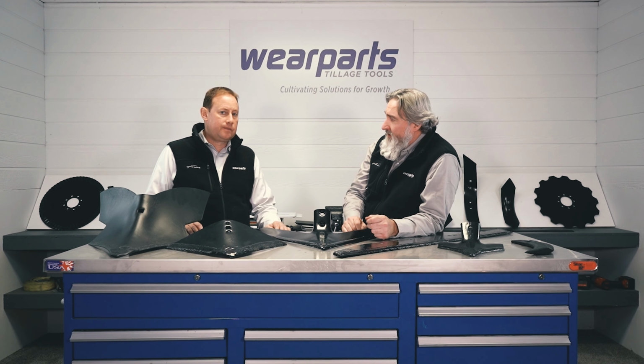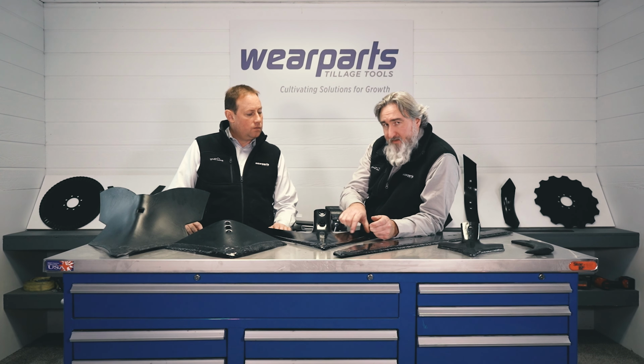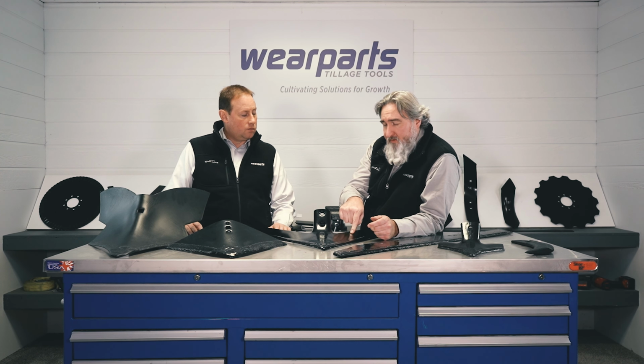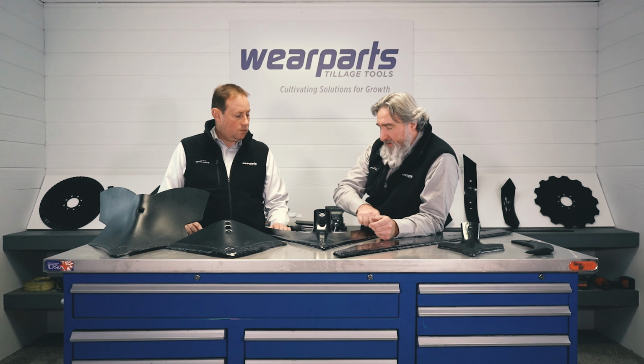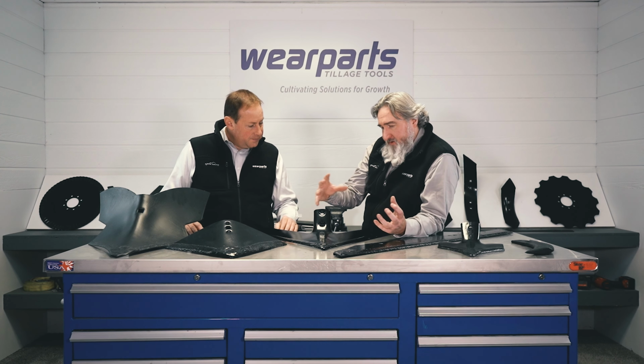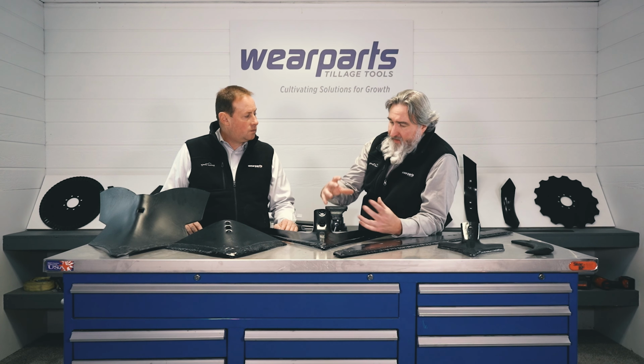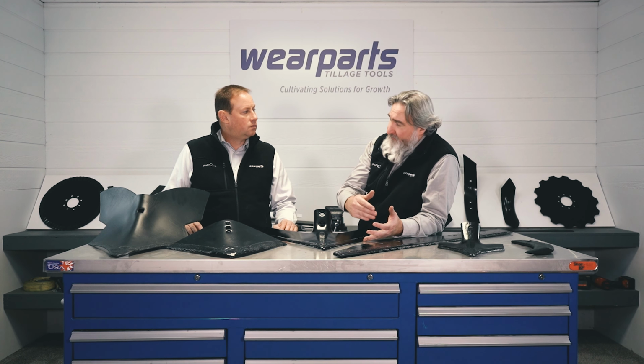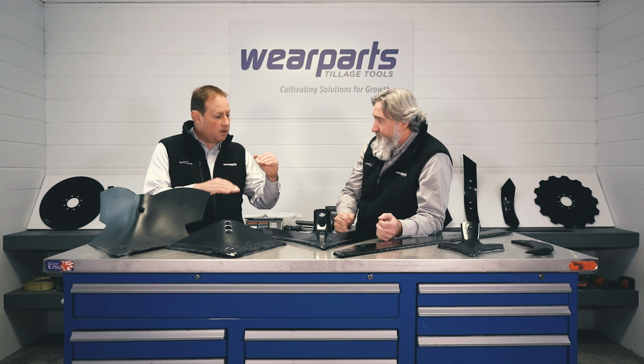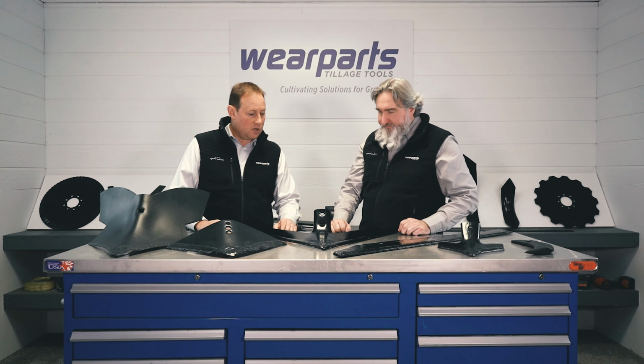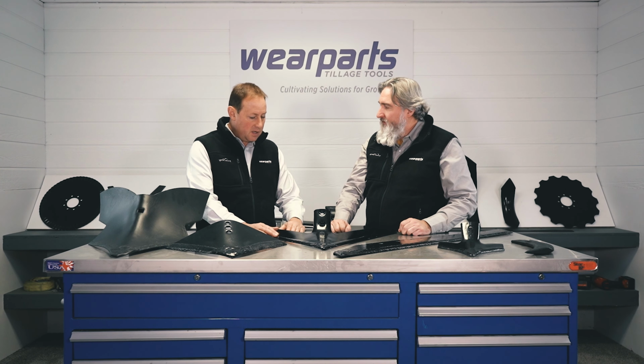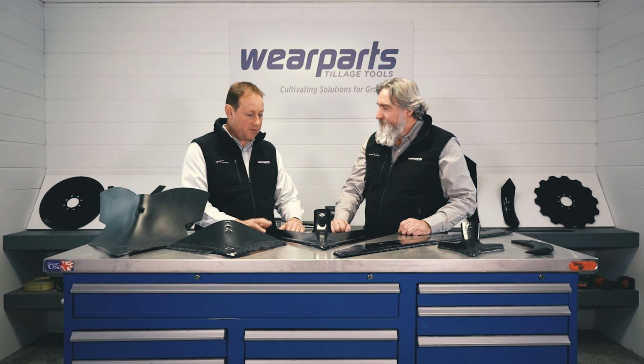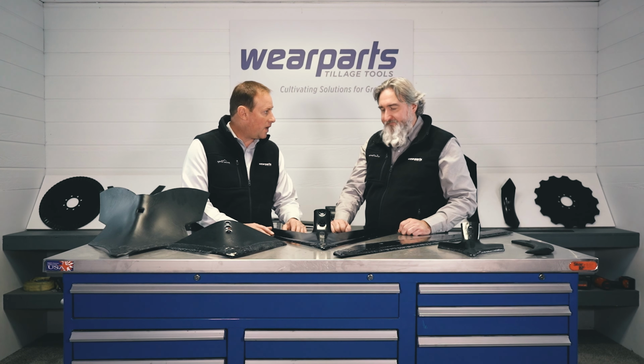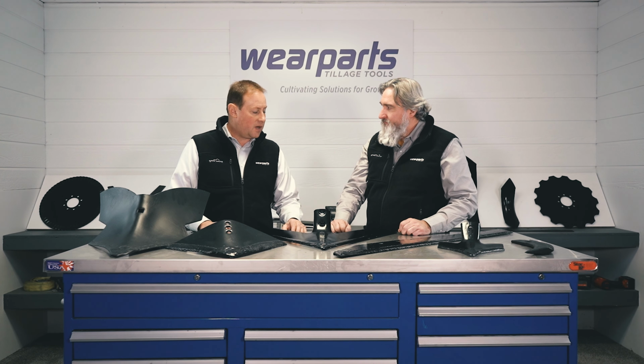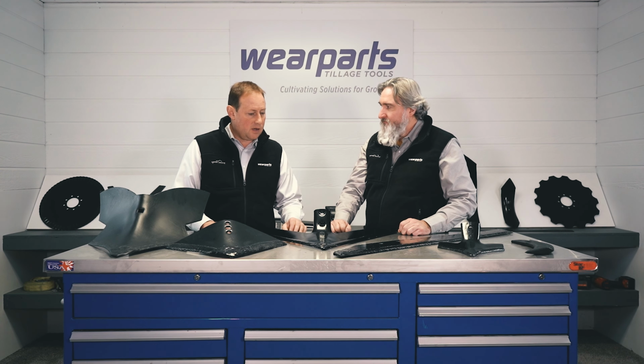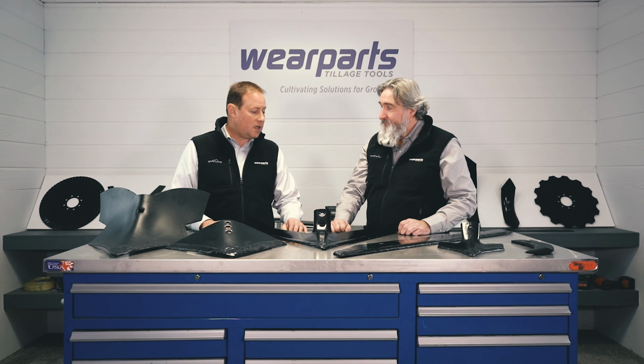And another advantage of that cooler temperature is you have two different shrink rates. You get two different types of metal here. The base material is going to cool down and heat up at a different rate than what that hard metal is. It makes sense. So as temperatures are changing, heating up, cooling down, if the difference is too much, then you could have cracking in either that hard facing or in that base material, on the varying degrees as it cools down. So with this cold metal transfer, if you check the heat directly after you've run this bead, it's running 400, 500 degrees, whereas your standard hard facing methods, whether it's oxy-fuel or CV welding, you're running up 1,200 to 1,500 degrees of heat, so a lot more heat.